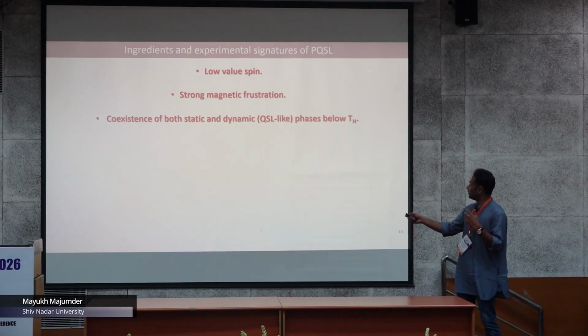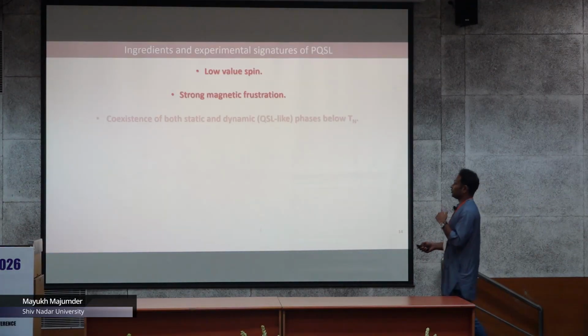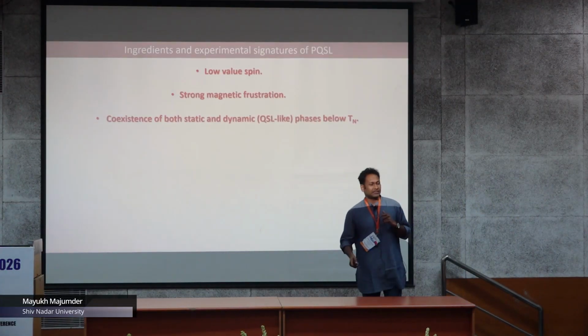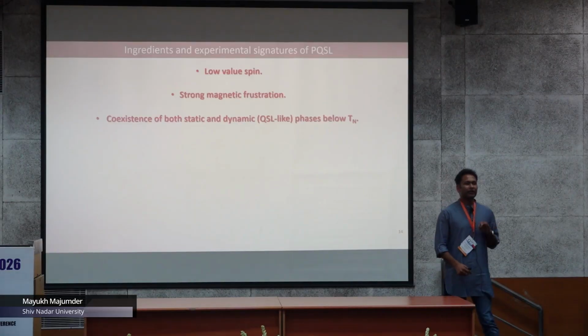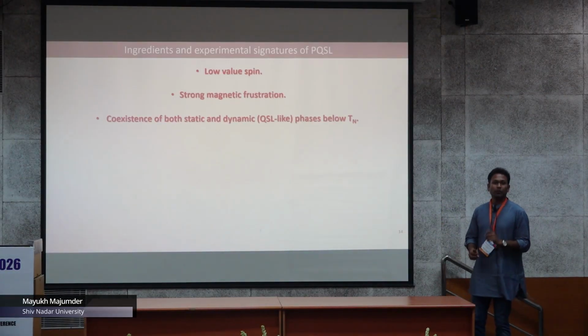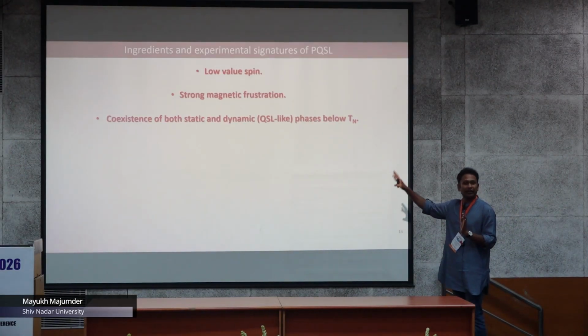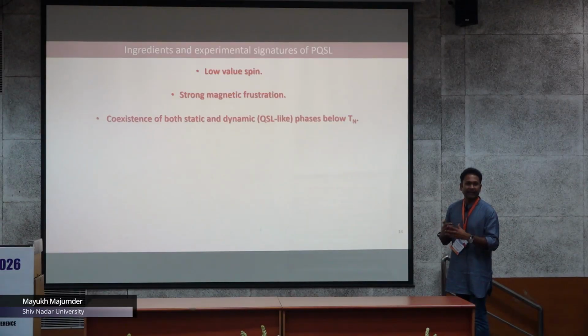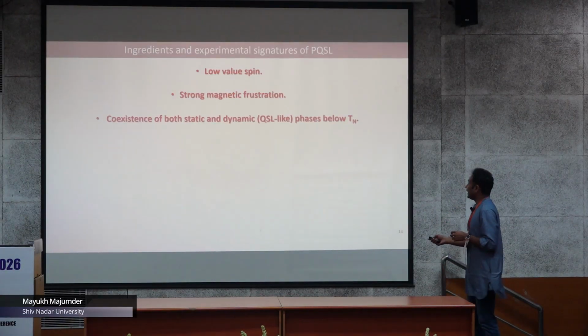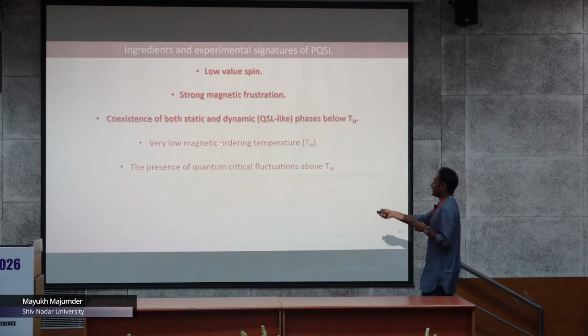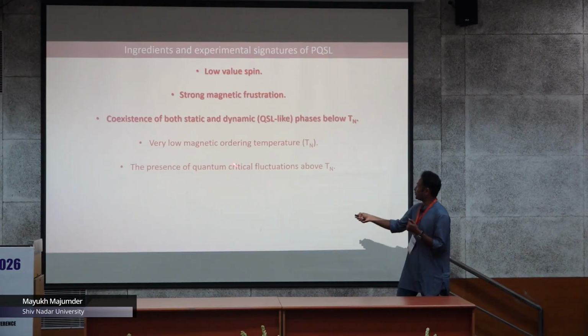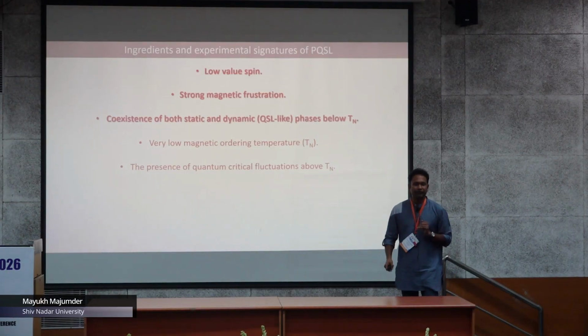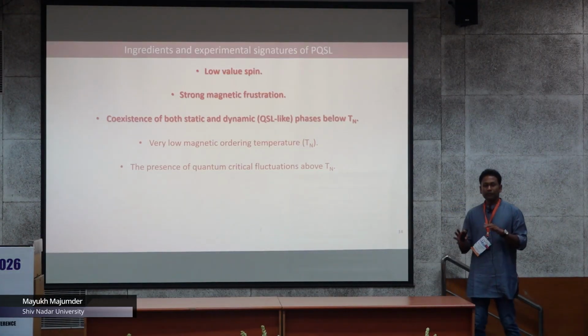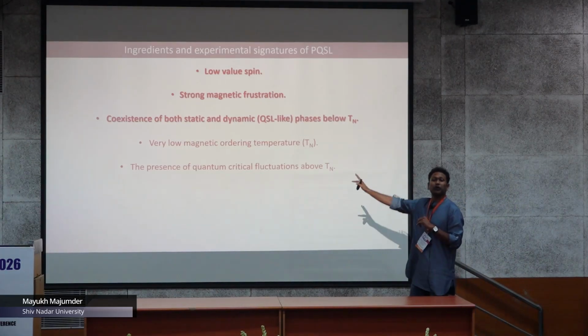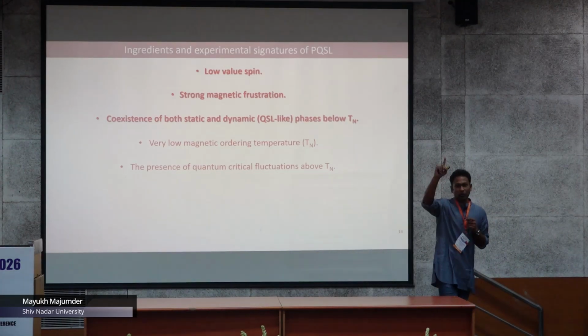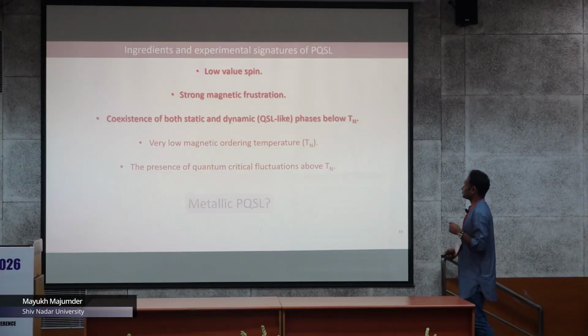Of course, you have to have frustration, and the most important point is that what people have seen is that the proximate quantum spin liquid state has a coexistence of both static and dynamical quantum spin liquid like state. Okay, coexistence of both of them. And the last 2 points, indicating very low ordering temperature and the presence of some quantum fluctuation above the phase transition temperature, are not mandatory, because those 2 points are only going to be valid if I consider the first possibility I showed you earlier. Okay, fine.